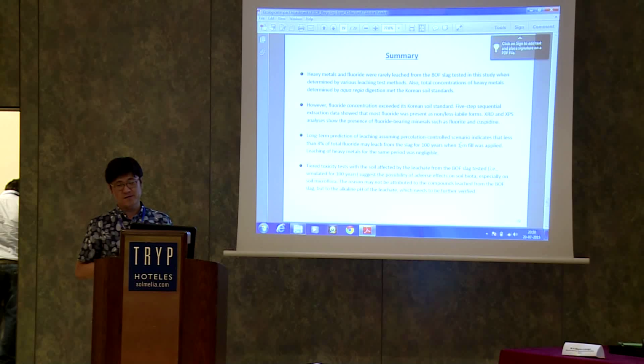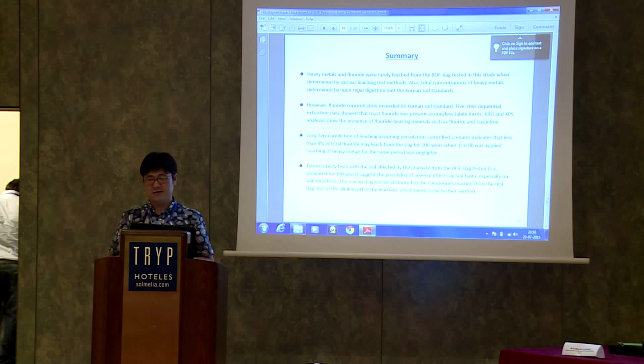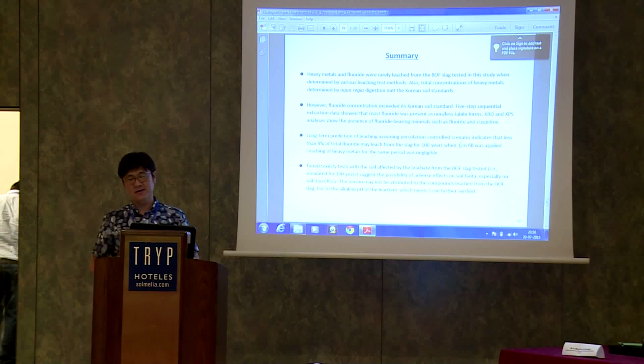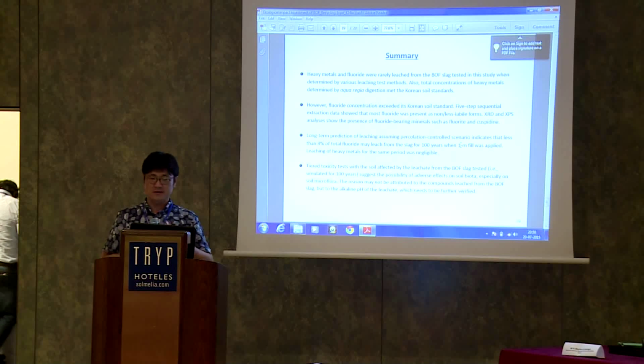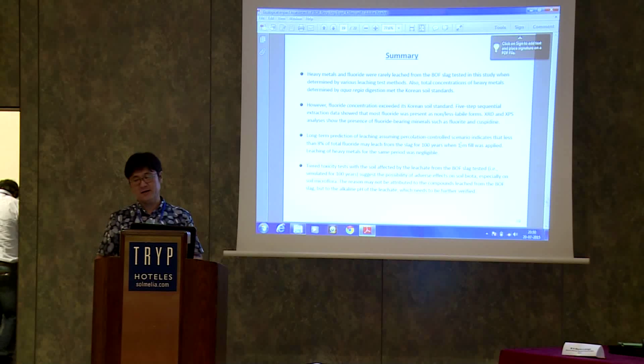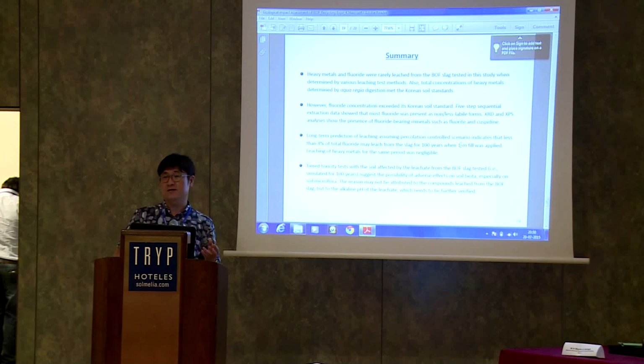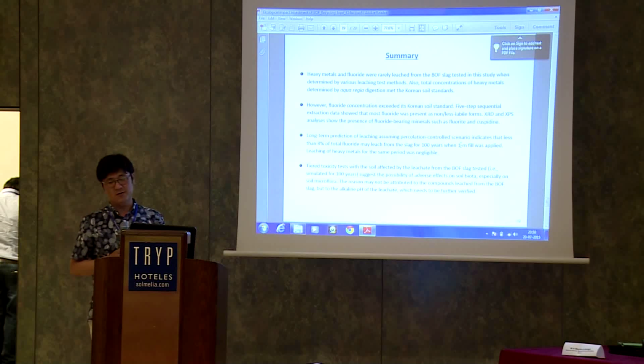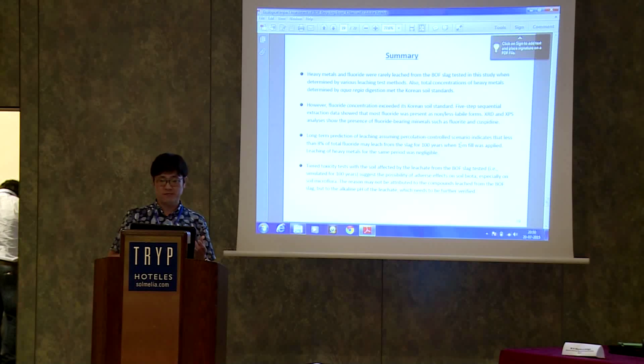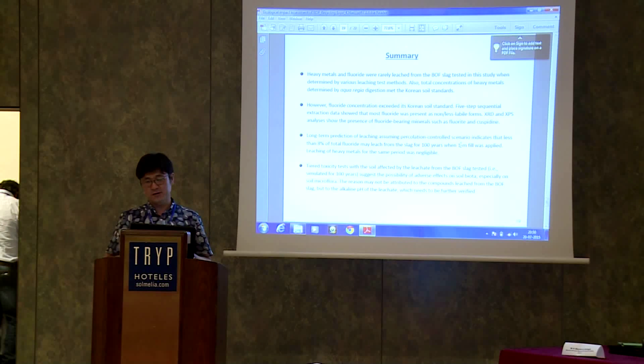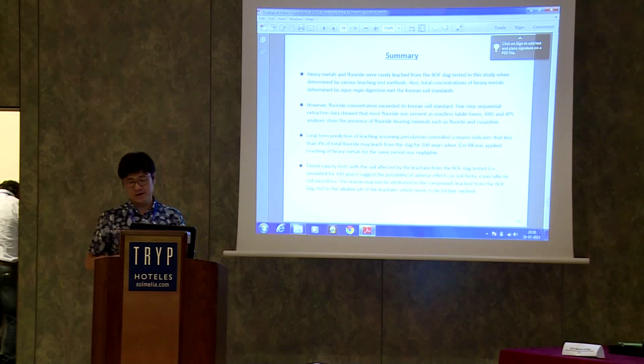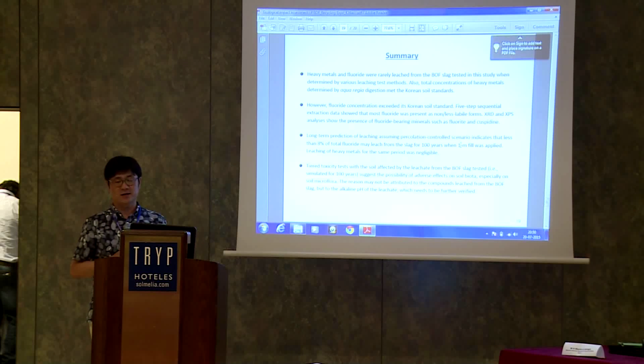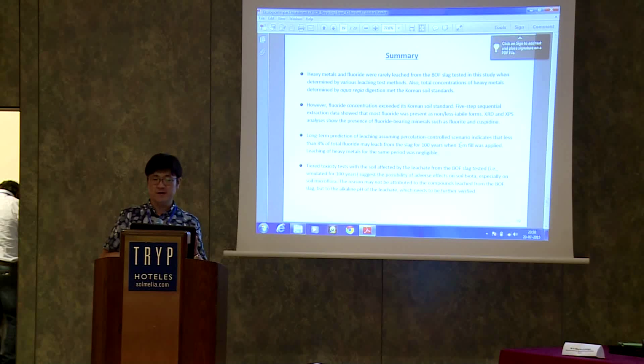And our experiment shows the 5-step sequential extraction data. So fluorine or fluoride is present in labile or less labile forms. And XRD and XPS analysis shows that they are minerals, which means they are not leachable, and therefore not bioavailable. Long-term prediction shows that the fluoride, about 8% of the total, can be released when applied to a 1 meter field for 100 years. And leaching of other heavy metals may not be significant.